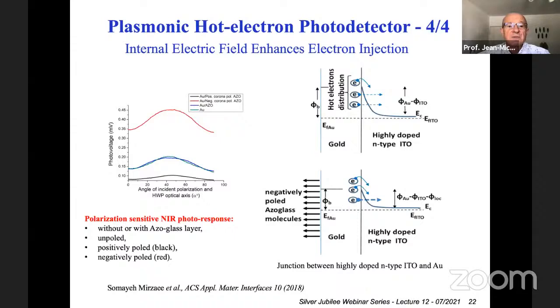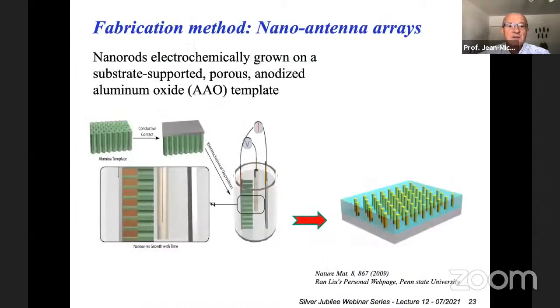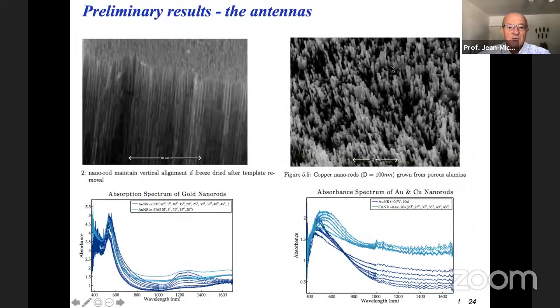So what I will do is skip a little bit of the part, like the fabrication method for the nano antennas, because by fabricating nano antennas, we can tune the frequency of resonance of the plasmonic. For instance, here is an example. We fabricated these, which are gold, and these are copper. With the gold, we can have quite monodispersed nanoparticles. These are 200 nanometer long nanoparticles embedded into an aluminum oxide matrix membrane, exactly. And the antennas create an absorption which is in the range of 1.2 to 1.4 microns. That can be tuned more in the infrared by tuning the length.